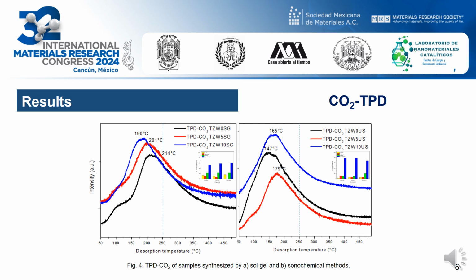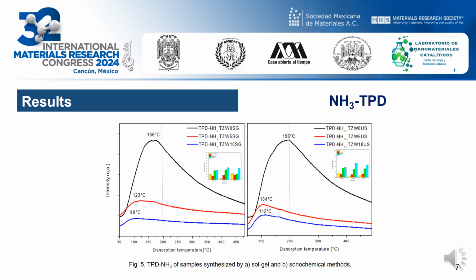Besides, the quantification of the basic and acid sites was carried out by carbon dioxide and ammonia temperature-programmed desorption. Carbon dioxide TPD shows that the energies are higher for the sol-gel samples with a greater strength, with very weak basic sites observed on the sample without tungsten. On the other hand, the ammonia TPD results evidence that the surface ammonia interaction energy and the amount of acid sites associated with the weak acid sites is higher in the catalyst synthesized by the sol-gel method without tungsten, and once the tungsten is added, the material synthesized by sonochemistry shows higher basicity and higher acidity.